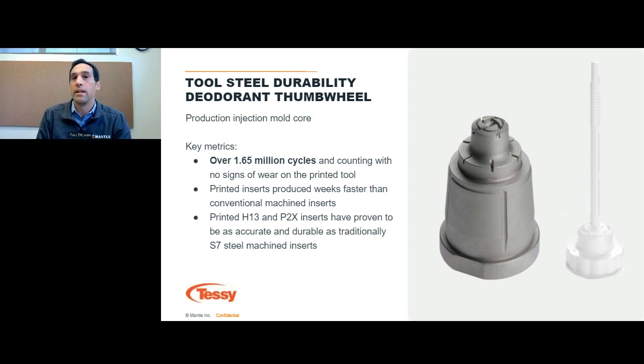And so what they did is they replaced 2 of those inserts with Mantle printed inserts. I'm holding up one of them here as an example. These inserts, we printed one in our H13 steel, one in our P20 steel. And Tessy did a minor amount of finishing, didn't touch any of the part detail, just did a little finishing around the sides in order to drop it into their mold base. And then put it in the mold base. This is over 1.5 years ago, and they have been running ever since. And so this is now over 1.65 million cycles and counting, with no signs of wear on the printed tool.